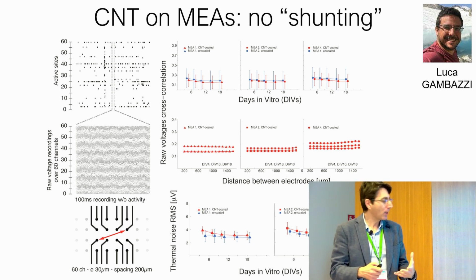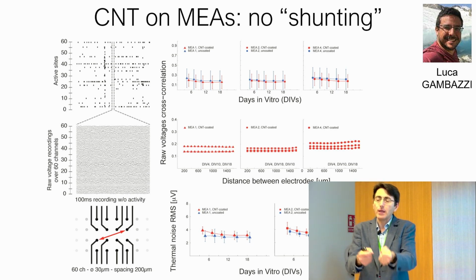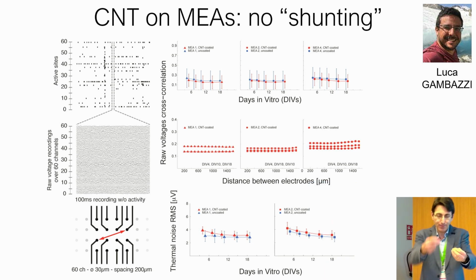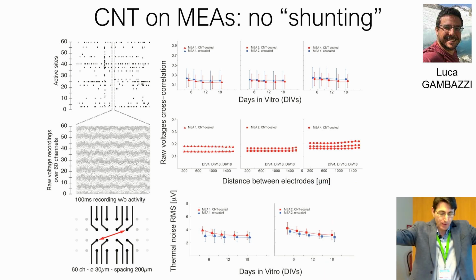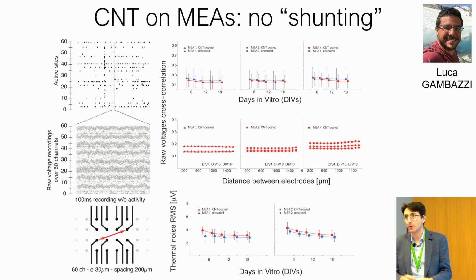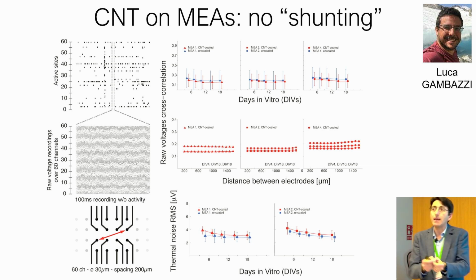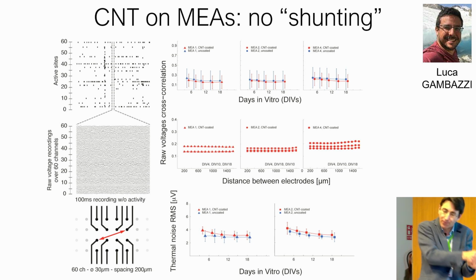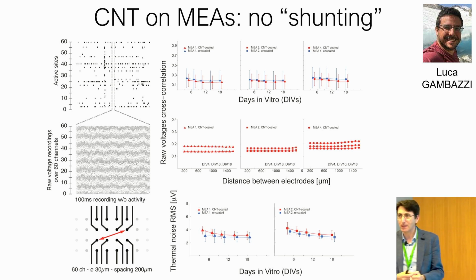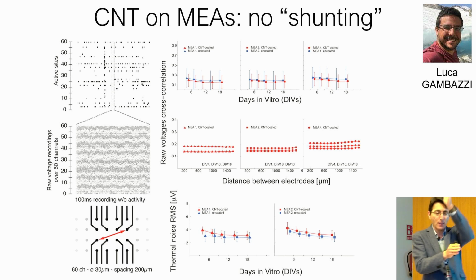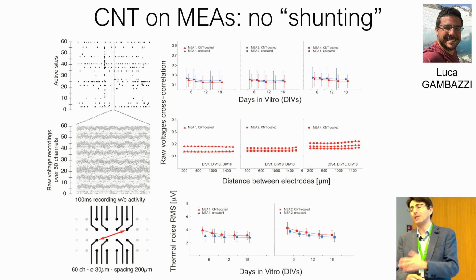This was my fear, because indeed they are electrically conductive. And so if I have several contacts, maybe if I put indiscriminately carbon nanotubes over the entire substrate, I will basically shunt the electrodes. But this was not the case. First, because we could detect signals, and these neuronal signals were not sub-millisecond or sub-microsecond synchronized, so there was no crosstalk between channels.